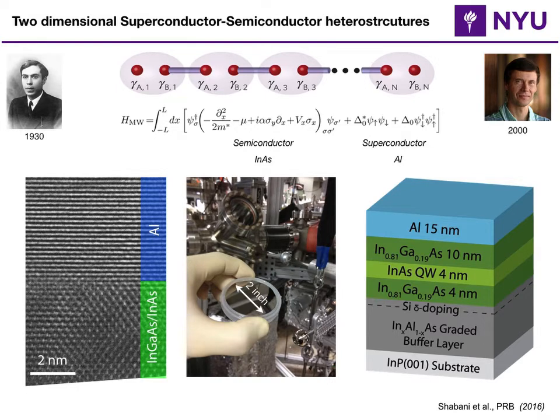So in 2018, instead of nanowires, we were looking at 2DEGs and wafers. We grew these indium arsenide quantum wells near the surface and then managed to put epitaxial aluminum on top of them. And the trick was to grow aluminum in a 111 direction compared to the whole other stack that is basically a 100 structure. And so once you promote that structure, you can see the TEM image on the left side, that the interface is quite pristine, and you can see a clear distinction between the quantum well and the superconductor.